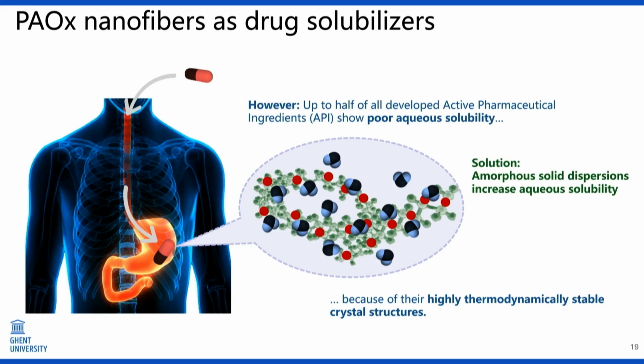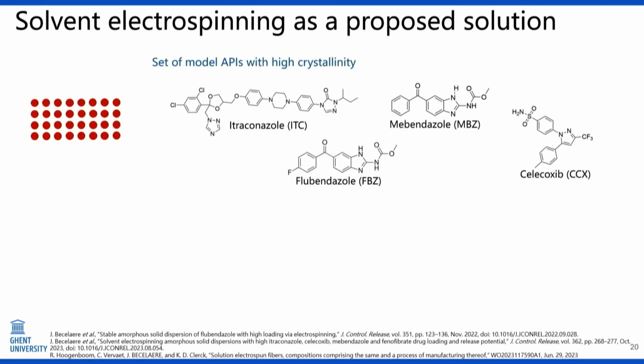Then you can only have drug loadings of 10%, which is of course far too low. And that's where we came in and we introduced electrospinning, and our hypothesis was that electrospinning, since we have such a fast evaporation of the solvent, we can suppress the kinetics and we will be able to produce amorphous solid dispersions. So that's what we did.